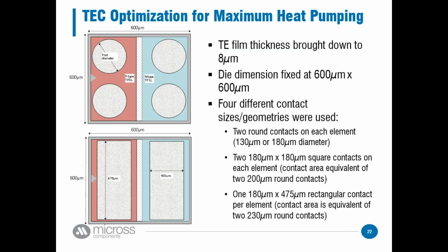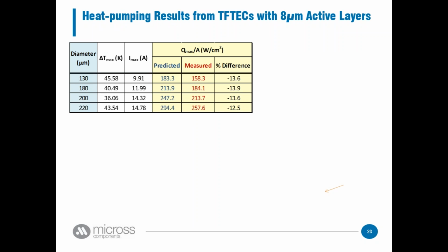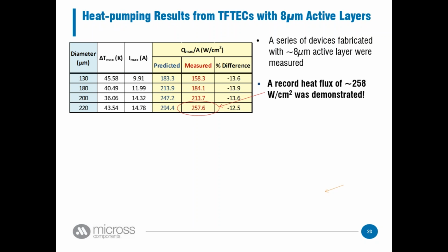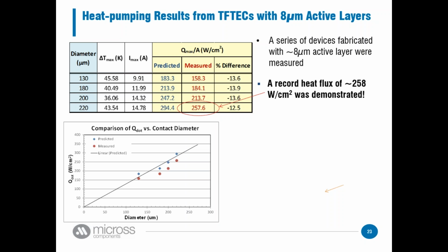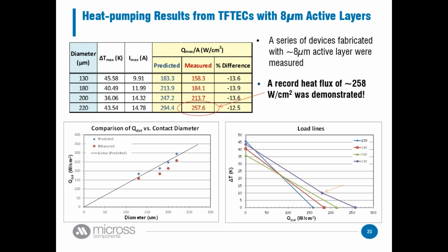Could we actually get better than this 90-100 watt per centimeter squared? And the answer is, we did. We got a lot better. We got over 250 watts per centimeter squared. Now again, the ones people are buying off the shelves, again, are 10. Laird, one of the companies that spun out from our RTI group, they make thin film thermoelectrics too, but even with those, they only get something like 70, 80 watts per centimeter squared. So these results were just crazy. 250 watts per centimeter squared was sort of a world record.